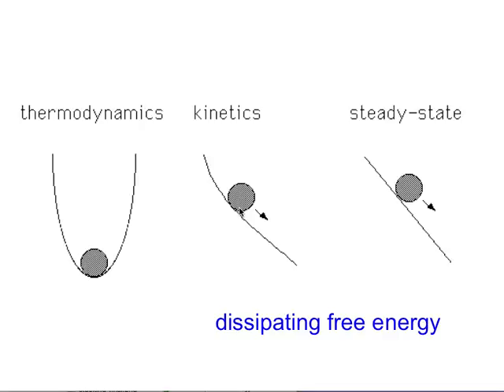So thermodynamics deals with equilibrium. That means there's no change no matter how long you observe the system. Kinetics is the situation illustrated in the middle, where the driving force might be changing during the course of the transformation because the composition of the matrix is changing. And steady state is when the rate of energy dissipation is constant. Okay, is everyone happy with that? So kinetic theory is very difficult, because there are just too many variables involved. But the steady state allows us to make an approximation between kinetics and thermodynamics. Okay, so we are going to refer to the steady state.